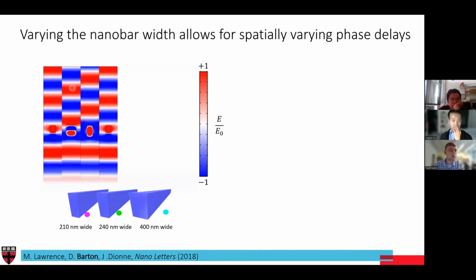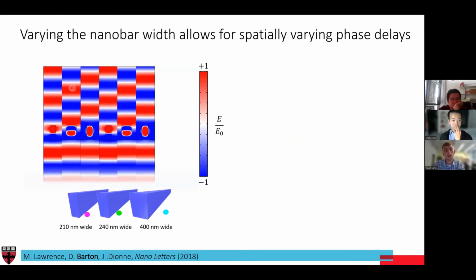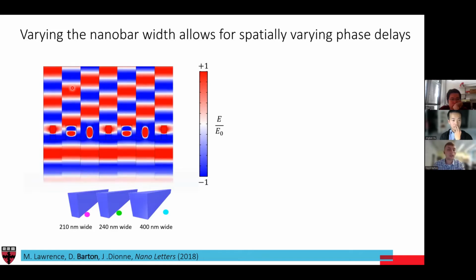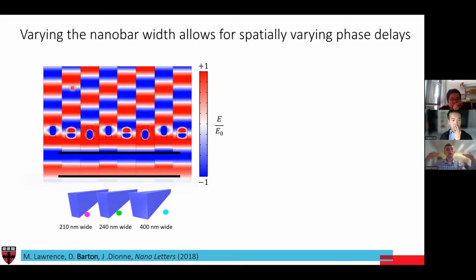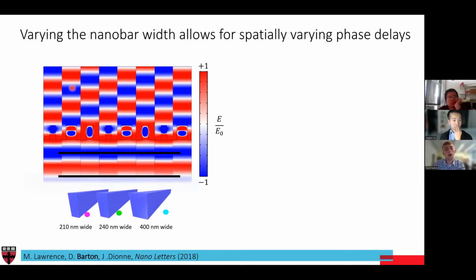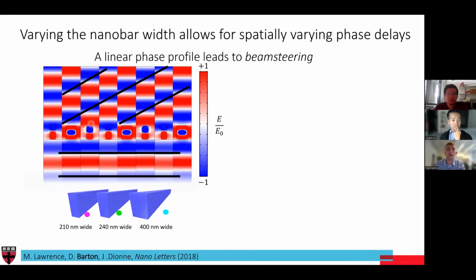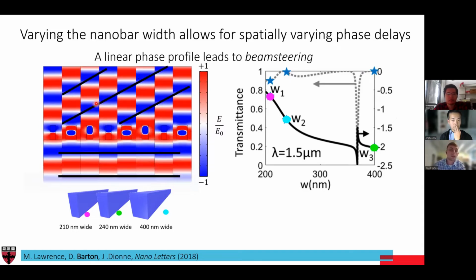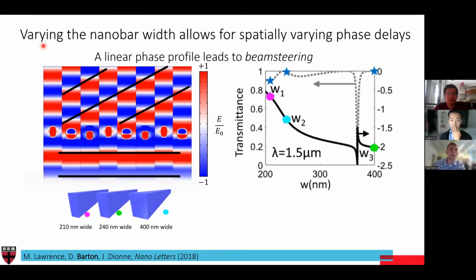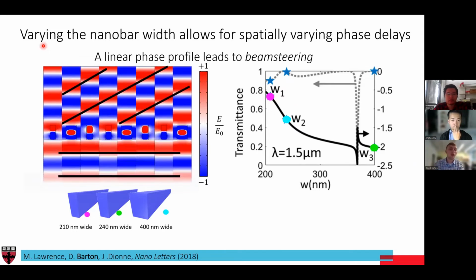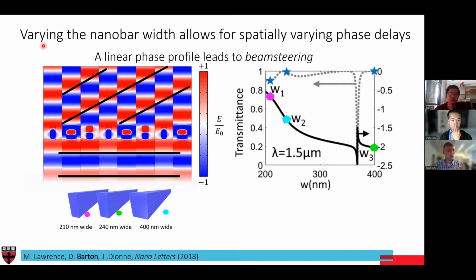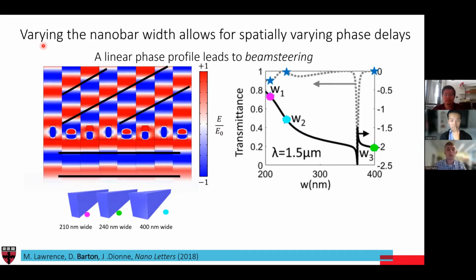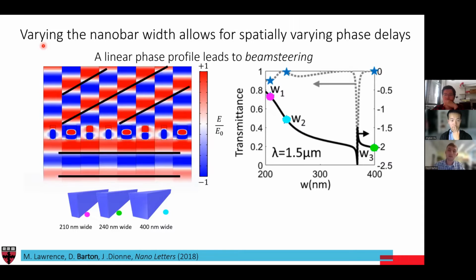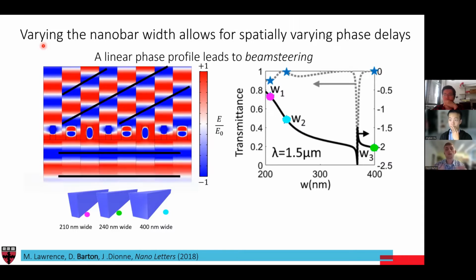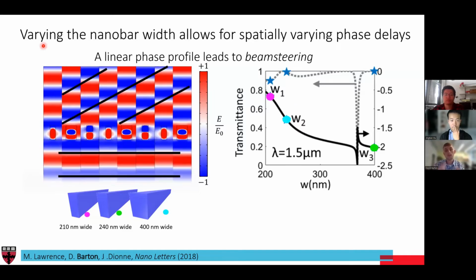And if I continue to put these in line with each other, what we find is that while we have a well-defined wave coming in that's propagating directly up, the individual phases of these elements build up and allow light to be redirected to a well-defined angle. In this case, light is now being directed up and to the left simply by changing the structure of the underlying material. If anyone has worked in this space, what we're doing is changing the width of these bars, and looking at the amplitude and the phase response of the scattered light. We're choosing elements that have well-defined phase differences that we can use to build our structure.